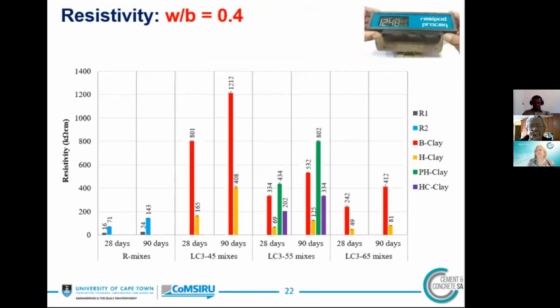Now coming to resistivity, here's the case of 0.4 water binder ratio. The LC3 mixes, especially mixes with B clay and HC clay, have very high resistivity values compared to reference mixes. And you can see LC3 mixes with H clay have low values compared to the mixes with B clay and HC clay, but better than the reference mixes. So this in general means that the LC3 mixes are less permeable than the reference mixes.